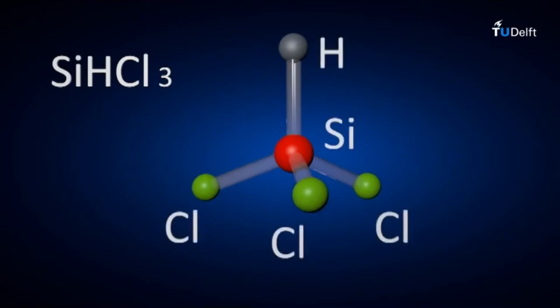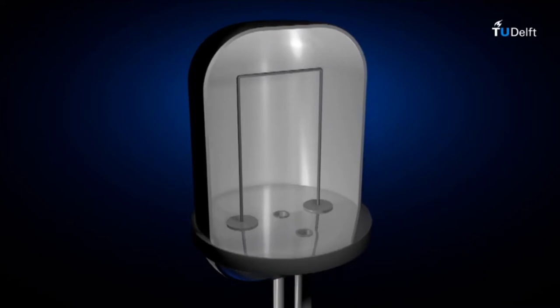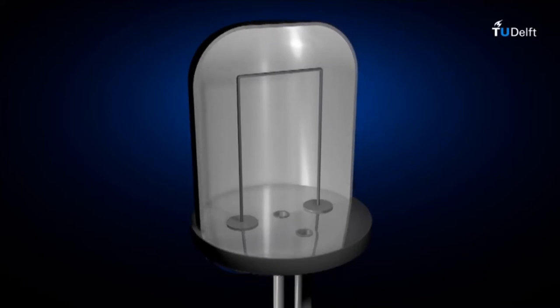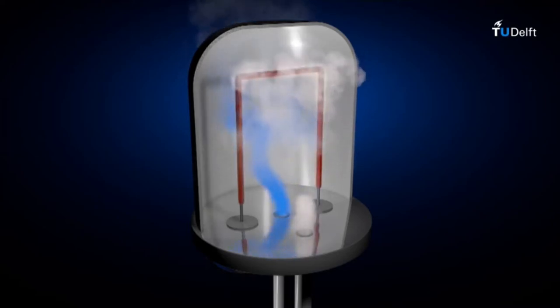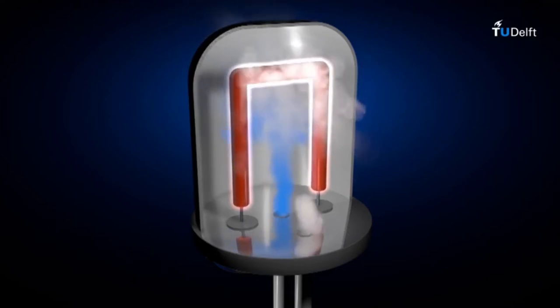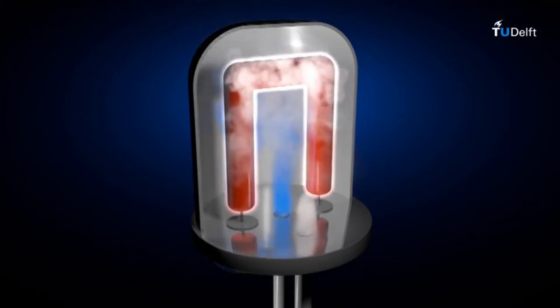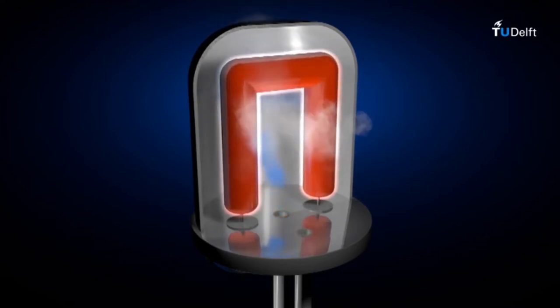The trichlorosilane gas is cooled and liquefied. Impurities with higher or lower boiling points are then removed using distillation. The purified trichlorosilane is evaporated again in a different reactor and mixed with hydrogen gas. Trichlorosilane reacts with the hot rods, which are at a high temperature of 850 up to 1050 degrees Celsius. The silicon atoms are deposited on the rod, whereas the chlorine and hydrogen atoms are desorbed from the surface of the rod back into the gas phase. As a result, a pure silicon material is grown, and this deposition method is called chemical vapor deposition.